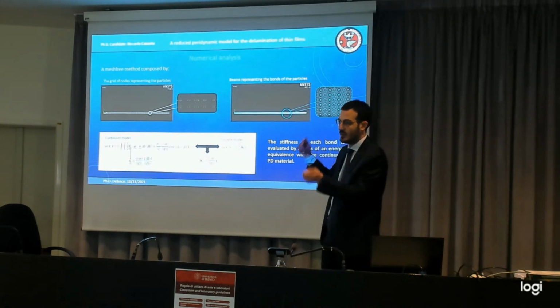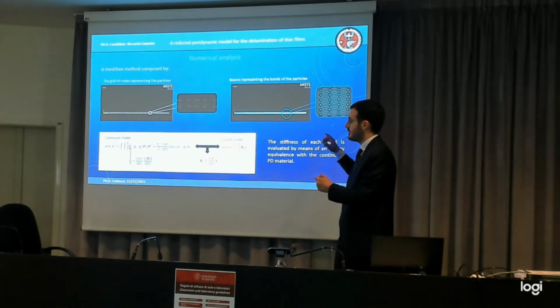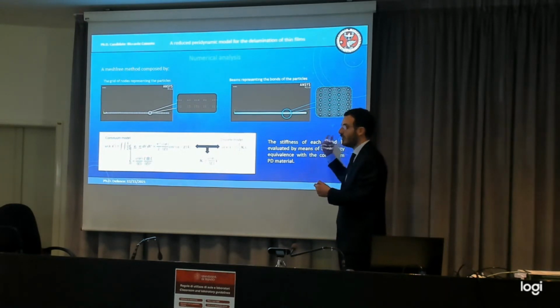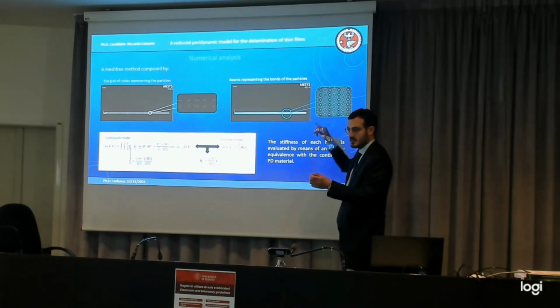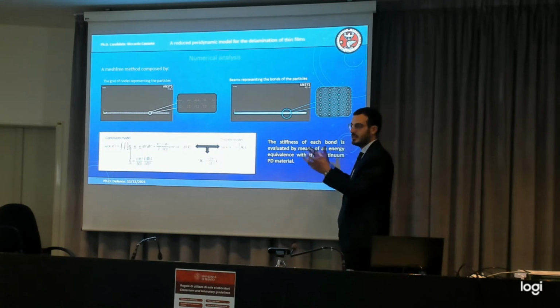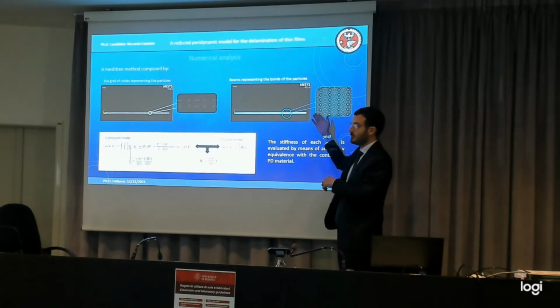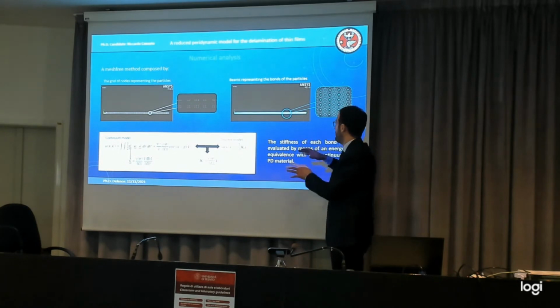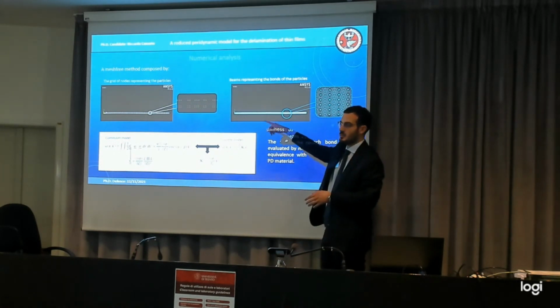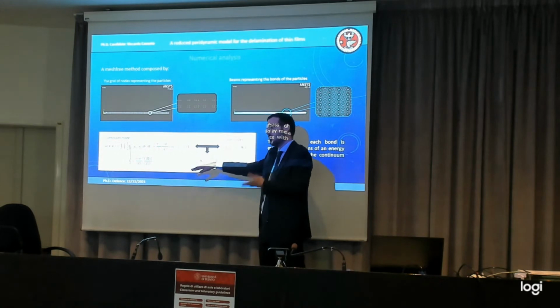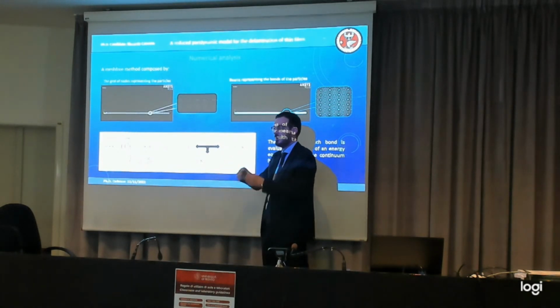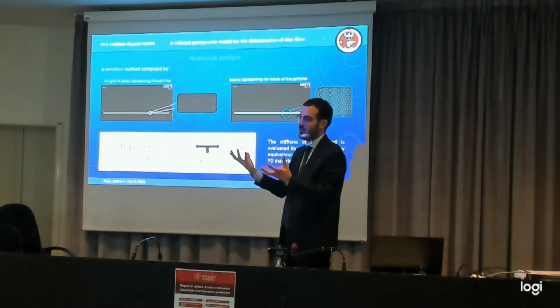Bond-based peridynamic is just one of the possible models. There are more advanced formulations that avoid the fact that this is a centered trusses, so the Poisson ratio is fixed. You can free the Poisson ratio by upgrading the bond-based formulation. Basically, what is happening is that you imagine a couple of points with a more complex energy, not representable anymore by trusses, but they have an interaction which is not defined by a single parameter, but rather a matrix, giving you the relative stiffness for all the relative displacement.